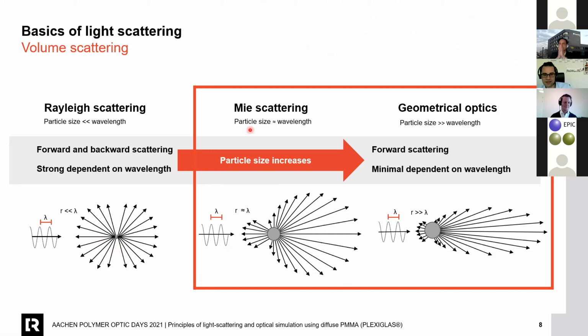Mie scattering means the particle size is roughly the same size as the wavelength or a little bit above. So Mie scattering shows a strong forward scattering, but as well 20 to 30% backward scattering, reflective scattering. In a lot of real life applications, this light is lost. So if we go forward to geometrical optics, we increase the particle size again. It must be much, much bigger than the wavelength of the incoming light. Forward scattering shows a lower scattering power, as you can see here, but you minimize the reflective scattering. It's an advantage, more efficient in regard to energy efficiency, but the scattering power is lower.